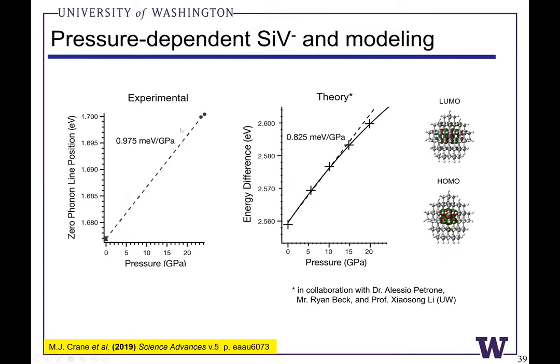Our experimental results showed a pressure dependent shift of about 1 meV per GPa for the negatively charged silicon split vacancy center. And their theoretical calculations were very close to this. They were using a parameterized lattice constant from bulk diamond to compute the shift in the lattice constant as a function of pressure, then feeding that into their DFT model. And they predicted a pressure dependent shift of the silicon vacancy zero phonon line of about 0.8 meV per GPa.